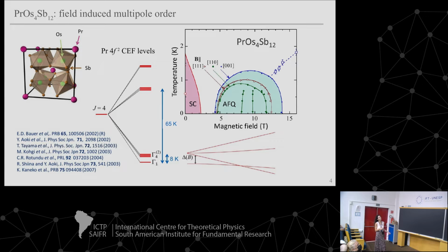So the important physics for this part of the phase diagram is the crystal field physics. Praseodymium has a J equal to 4 multiplet. This is the crystal field splitting then. And we have a gamma 1 non-magnetic singlet ground state and a gamma 4 triplet first excited state. These are close together. The higher levels are much further away, 65, even a bit more Kelvin. So we can treat this as a kind of two-level system.